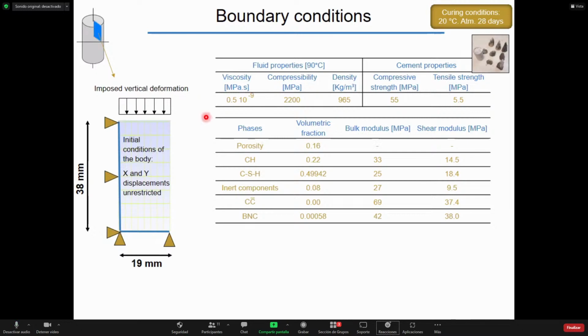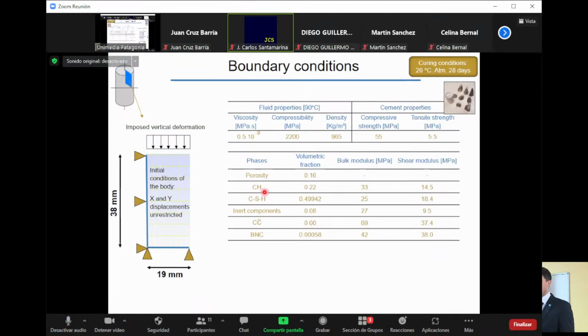So, to simulate our samples, we took a quarter of the cylindrical samples that we used in our tests, and we took the fluid properties at 90 degrees of viscosity, compressibility, and density, and the cement properties taken from the uniaxial compressive strength test. To determine the phases of cement, porosity was taken from the MIP test results. The portlandite content was taken from the TGA analysis. And initially, we didn't consider any carbonates in the samples, and the content of bacterial nanocellulose used was the content that we added in the experimental test. The values of CSH and inert components were taken from literature, and the inert components are aluminates and anhydrous cement.